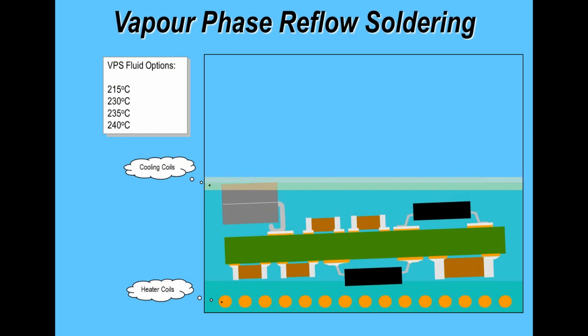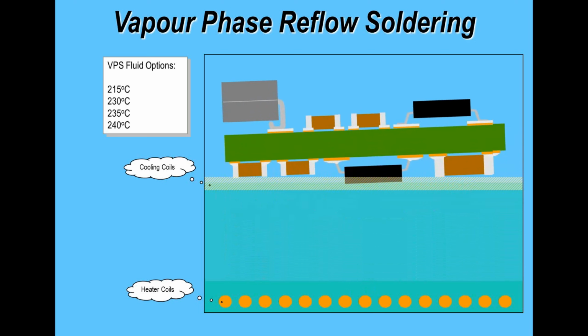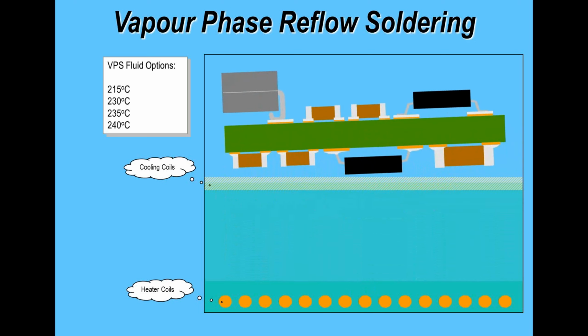For lead-free, typically you tend to find most customers of vapor phase systems use 230 boiling fluid, and that's fine for SAC alloys. If you're looking at tin copper alloys, you have to go really to 240 boiling temperature. Theoretically, you might be able to get away with a 235 boiling material, but 240 is more flexible.